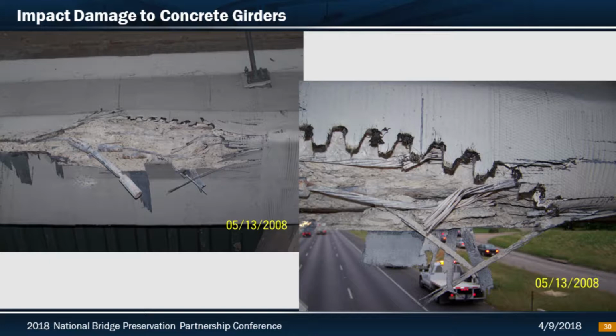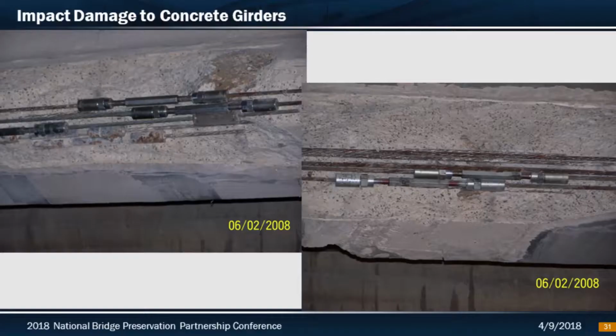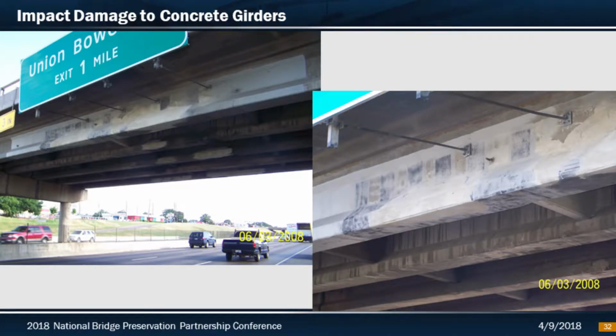You can tell here the CFRP fairly well mitigated the damage. It did take out a couple of the spliced tendons, but probably made it a lot less severe than it would have been without the CFRP. So I think this is when we started learning it acted as sacrificial reinforcing. This was the same second hit, on beams 2 and 3. We added additional cable splices, post-tensioned, and patched the material. Here's the end result with the beam patched and the CFRP installed.